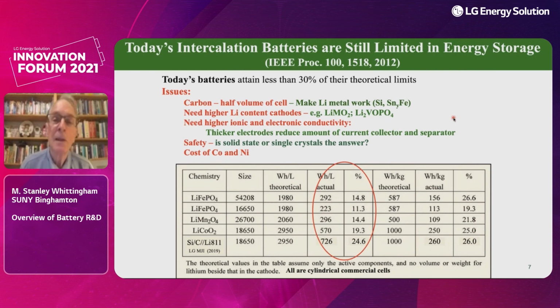So where do we stand now? A lot of people say the Nobel Prize was given out, therefore this R&D on batteries should be finished. It couldn't be further from the truth. If we actually look at today's batteries, they attain less than 30% of their theoretical limits. So we've got lots of opportunity there. And the highest capacity cell I found looking in the literature about a year ago was in fact an LG cell. This one attains almost 25% of the volumetric capacity and essentially the same on the gravimetric. And this has now the highest volumetric capacity of a commercial cell.